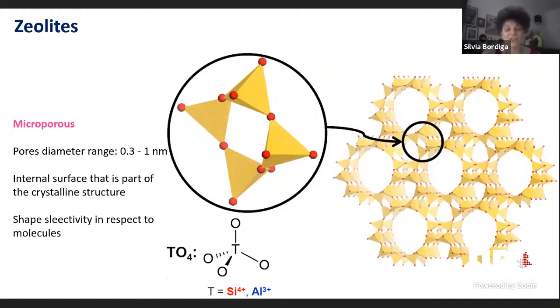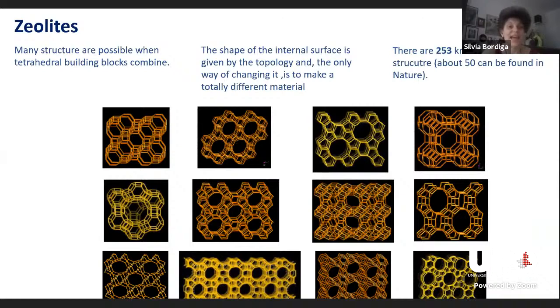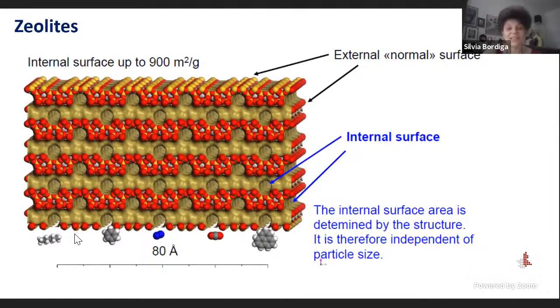Then we have the possibility to change the composition, and so adding the chemistry to the lattice properties. And we have many structures. And at the moment, we have more than 200 known zeolite structures, and some of them are also known in nature. Here I've taken some of the structures from the Atlas of Zeolites. And as you can see, we have structures with pores with the shape of channels, or cages where we can have a larger space inside. So the possibility is to have the mobility of molecules inside the channels, especially if the channels are interconnected, which is not the case of this zeolite, which has just straight channels as reported in the picture.